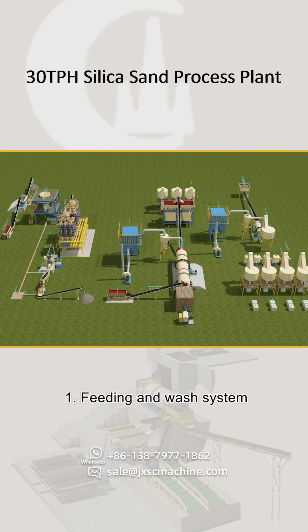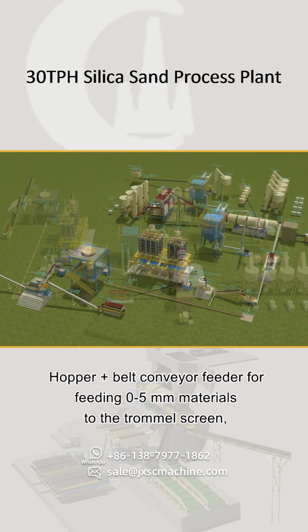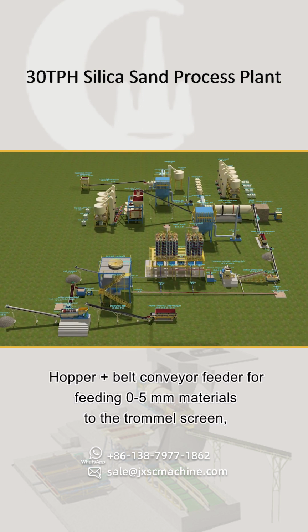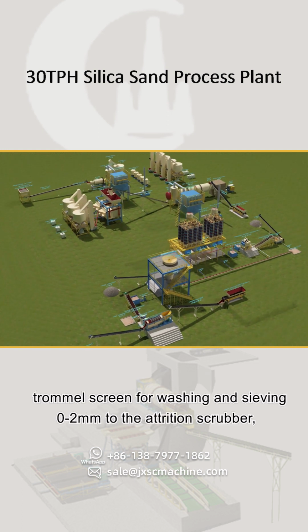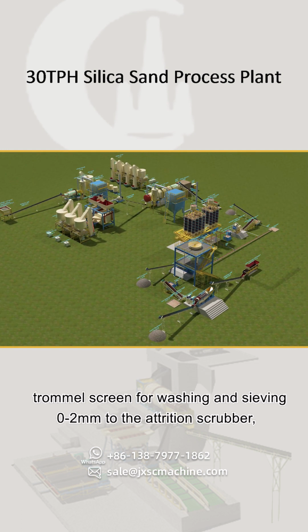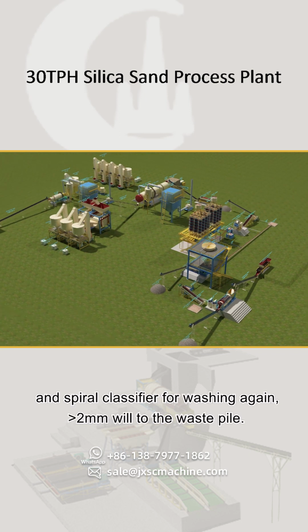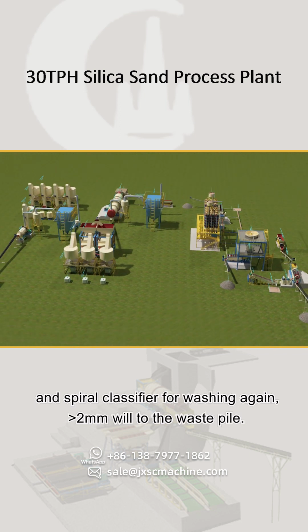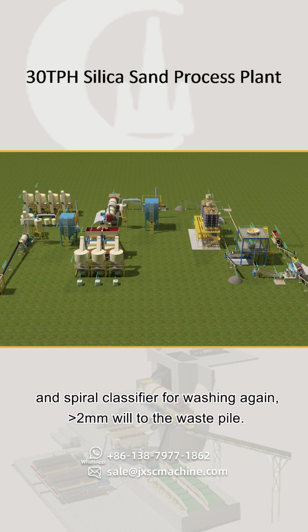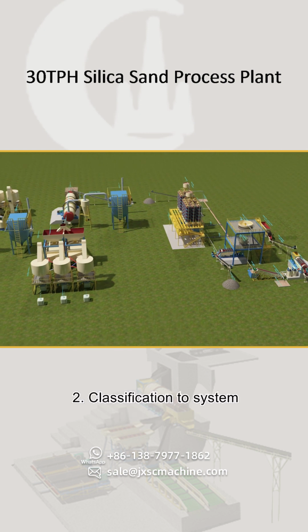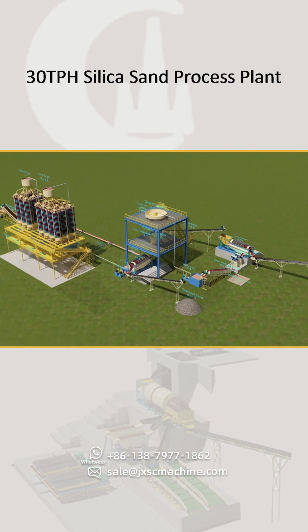1. Feeding and wash system. Hopper plus belt conveyor feeder for feeding 0 to 5 mm materials to the trommel screen for washing and sieving. 0 to 2 mm to the attrition scrubber and spiral classifier for washing again, more than 2 mm will go to the waste pile.